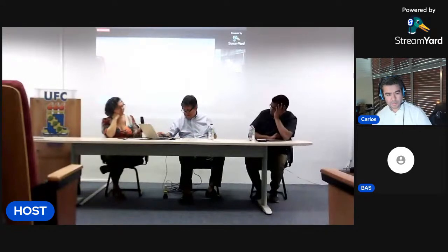Fully support that. It's very important. If you're working on removal of CO2 from flue gases, the faster it is, the better. Otherwise, you will have a mass transfer zone and your equipment will become large. And also you will struggle with purity, so you have to spend more energy. On the other side, if you want to remove CO2, for example, from other places like biogas, where you need to kind of force the adsorbent to not adsorb methane, you want the kinetics of CO2 to be as fast as possible, but without having any adsorption of methane. So in that case, the adsorption of methane has to be delayed, I would say.